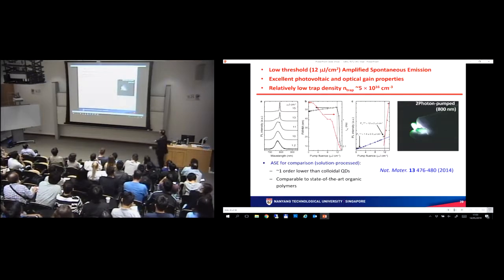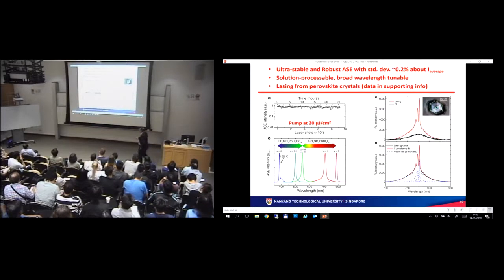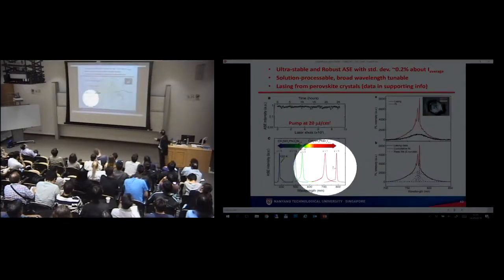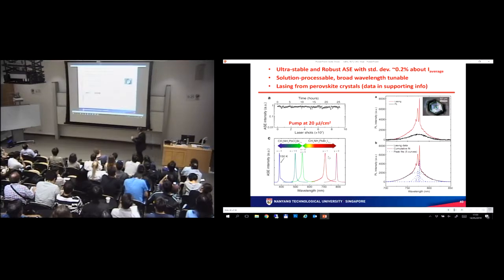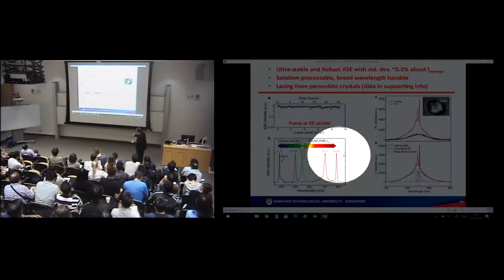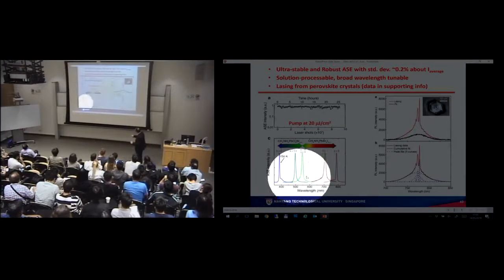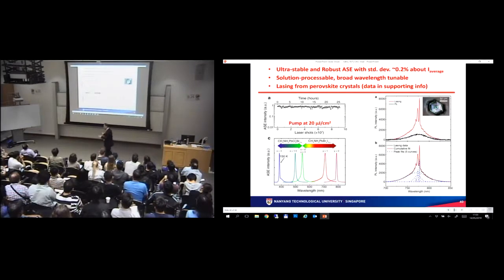So the finding here is that the threshold is fairly low. It's very easy, you hit it very easily, you get amplified spontaneous emission. And the significance is that, as a solution process material, you can easily mix and match the precursors, and then you can tune a broad emission range, ranging from 400 to 800 nanometers. That was demonstrated in this paper. We eventually extended the range to around 950 nanometers using tin-based perovskites. That means you go into the infrared. So in principle, you can tune your optical gain media to any wavelength within this range, from visible all the way to infrared, using this perovskite system.